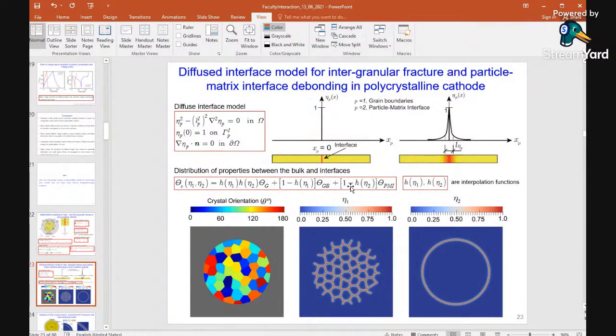In this case, we incorporated a diffuse interface model for this fracture. If there is a grain boundary, there is a junction, the sharp interface is diffused, and then we interpolate the material parameters. Actually, what is happening in the interface is that the interface is weak. So we assign a different amount of fracture energy or fracture strength for the grain boundaries. So grain boundaries are potential sites for crack evolution.